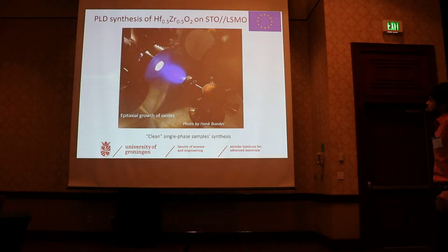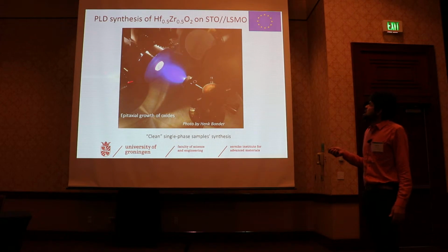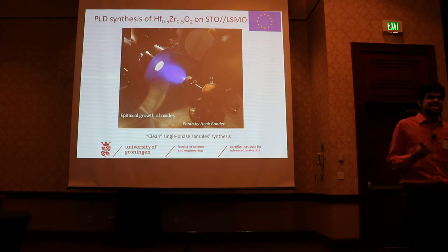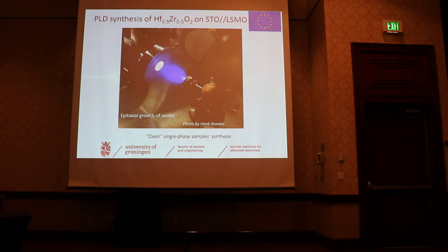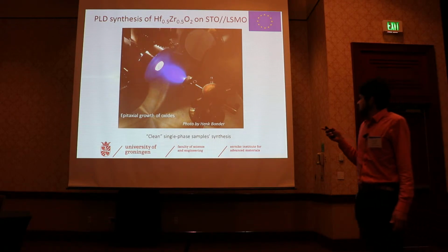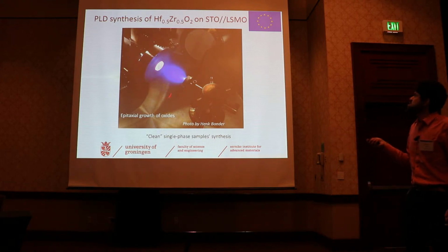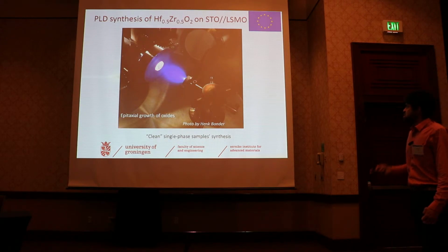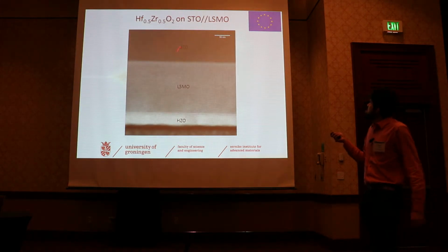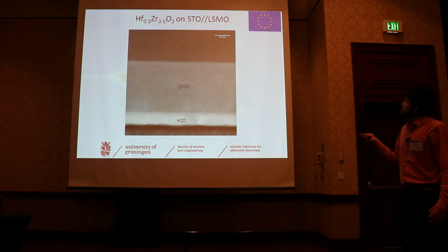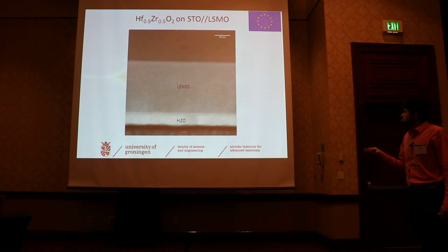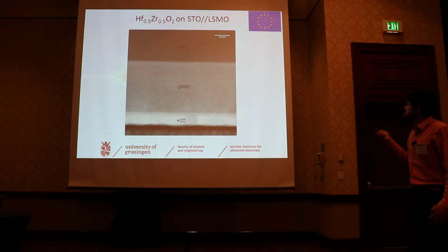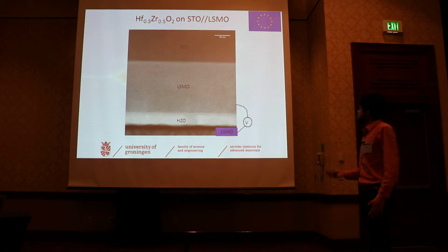Okay, so what we decided then was to actually synthesize single-phase samples. Single-crystalline is too much of a stretch, but single-phase samples, with the help of the one technique that we know the best, which is pulsed laser deposition. So here are our structures. We have a substrate, STO. LSMO is a back electrode, and we grow a very thin layer of hafnium zirconium oxide.